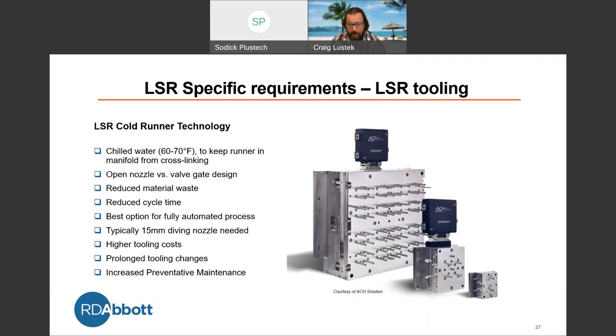You have reduced cycle time because we don't have to worry about trying to cure up that runner if the runner is heavier than the part. And then this is the best option for a fully automated process. We don't have to worry about design and engineering to try to remove the runner in process. Now we're only worried about removing the part itself. With this type of setup and system, we're typically running a 15 millimeter diving nozzle.